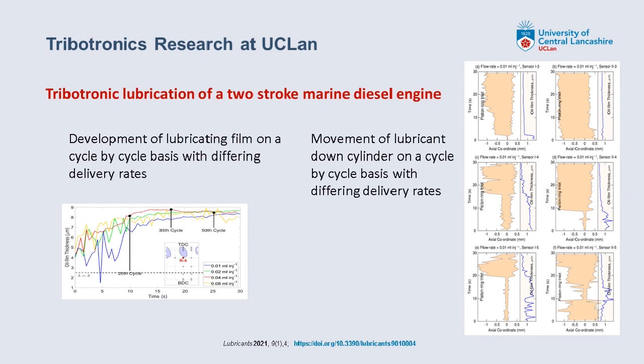One of the advantages of building a system like this is that it's allowed us to do some very interesting research to observe how lubricant moves around an engine. So this slide shows us on the bottom left what happens as we start the test rig, as it's not a firing engine, with no lubricant in, and inject lubricant in at different rates. You can see that the build-up of the hydrodynamic film happens at different rates, but they all stabilize out at roughly the same value. So at lower rates you can see, for example, the blue line, and at higher rates, for example, the red line. The graphs on the right are more complex.